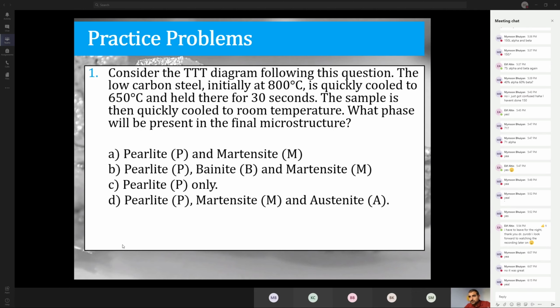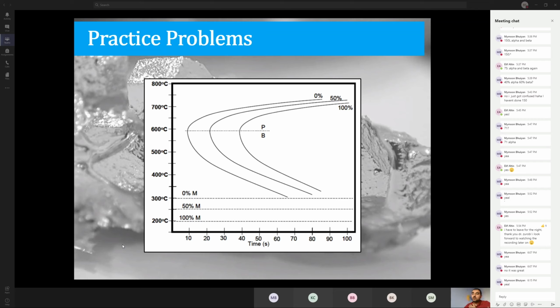A quick example, maybe? So this question says, I'm going to give you a TTT diagram, and you're going to tell me what happens if we go to 650 degrees and hold for 30 seconds. So here's the TTT diagram. To use the TTT diagram, you have to always start with gamma. It only works if you started with gamma. So we're going to assume we started at 800 degrees, and at 800 degrees, we start with 100% gamma. Okay? And it says we cool quickly to 650. So I come down, this is 650, and I hold for 30 seconds, and that's my 30 seconds. So at this point, after holding for 30 seconds, what do I have?